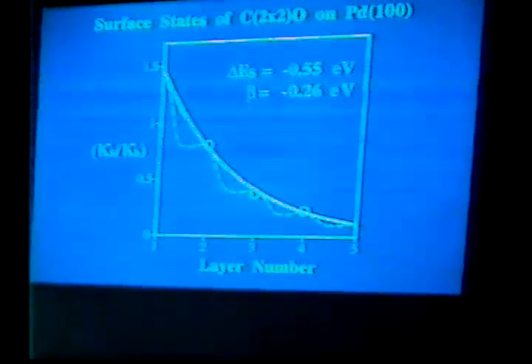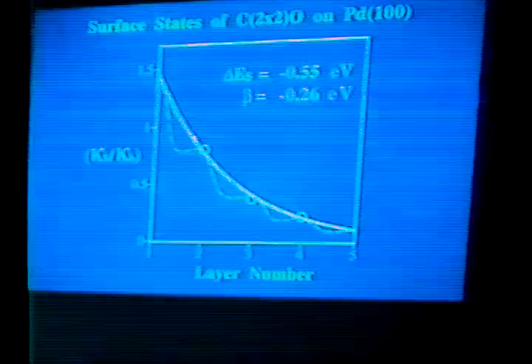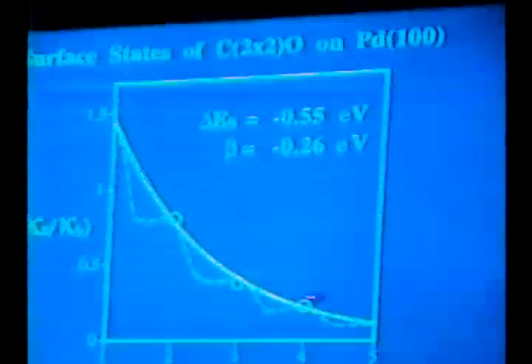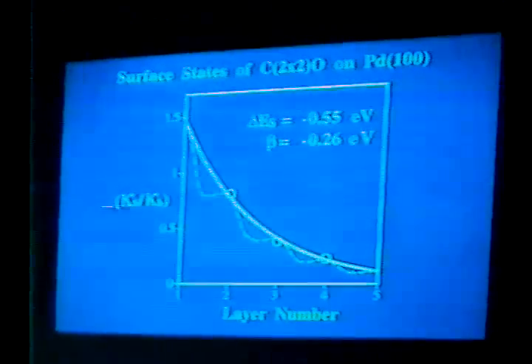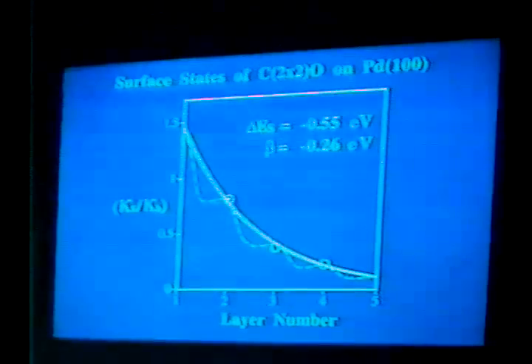It looks somewhat like the five mountains of China here. The normal emission, bulk and the surface state. The one that has a long path here shows more of the bulk intensity and less of the surface intensity, and so on. And the variation of these intensities is due to the diffraction that occurs on the surface atoms by the subsurface atoms' emissions, but now there are two kinds of subsurface emissions. One that has been induced by oxygen, and one that belongs to the bulk palladium.